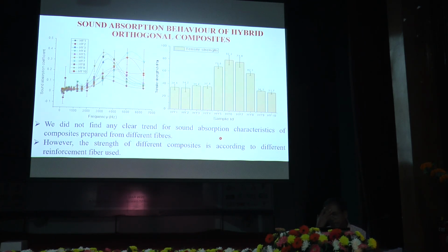Now, one thing we have done wrongly: we shouldn't have studied the acoustic absorption, we should have studied the sound transmission loss behavior. Also, in case of the thickness of the material, we have used 3 mm, but to have standard acoustic insulation, the material thickness should be higher, equal to or more than 5 mm.